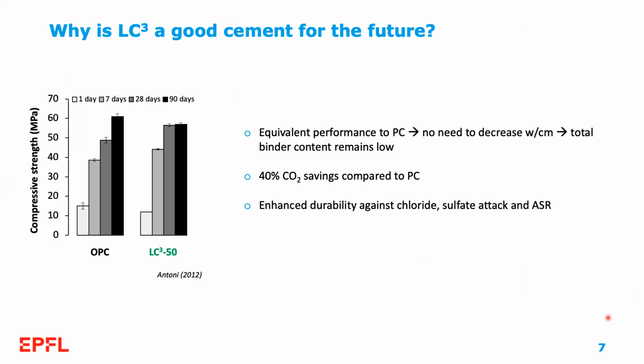LC3 is a good cement for the future. It offers equivalent performance to Portland cement. And this is very important because in this case, we do not need to decrease the water to cementitious materials ratio compared to PC in order to obtain a certain strength in our concrete. And this allows me to keep the binder content per cubic meter of concrete as low as I would use in a Portland cement scenario. This allows me to save 40% of CO2 compared to PC, and I have enhanced durability properties against chloride, sulfate